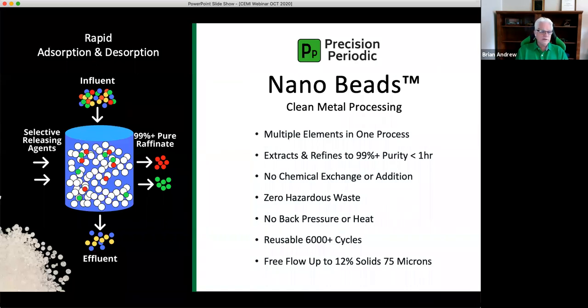How does it work? Basically, your liquor comes into the filter at full flow and washes over the filter. You can use gravity, for example, in our acid mine drainage, gravity's fine, so you run over the beads. After the beads begin to fill up, you stop the flow, and then you release the metals that it's held with individual selective releasing agents. So in the case of the gold situation, you would release, say, the mercury first, and then the gold second, or the arsenic first and the gold second, giving you pure gold chloride, in the case of using chlorides, and pure arsenic chloride.